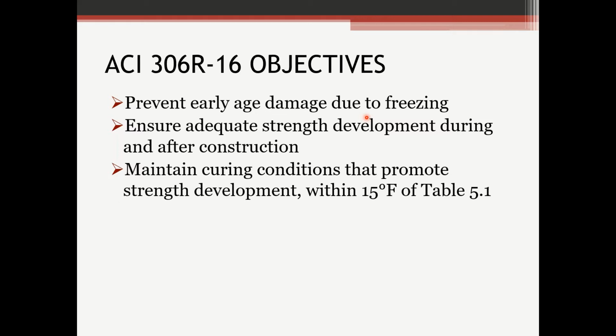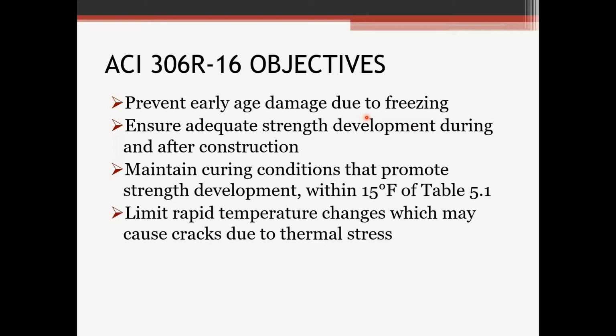Get within 15 degrees of table 5.1. I'll talk about table 5.1 here shortly, but table 5.1 has got minimum placement temperatures. There's a maximum placement temperature also. ACI recommends that you not be more than 15 degrees above the minimum placement temperature. So there's not a very big window in there for placement. Again, that's in 306R. Limit rapid temperature changes, which may cause cracks due to thermal stress. We'll talk about that.